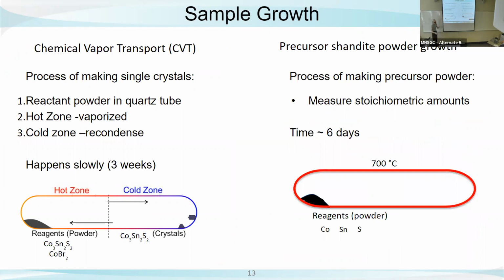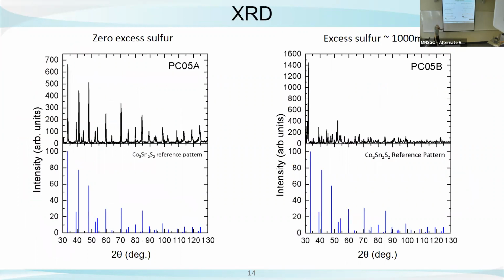And since our material is so new, we actually have to make a precursor powder. So that also takes around 6 days. So pretty lengthy process. But if you do it right, you end up with great results. But we would stick all of our stoichiometric amounts in there, heat it, and get one solid powder of just our cobalt-3 tin 2 sulfur 2. And so we did X-ray diffraction on these as well. And we did a study of adding extra sulfur because sometimes when you heat sulfur, it'll stay in the vapor phase and not go in and recondense. So we did a study just to make sure that we had the right sulfur content.